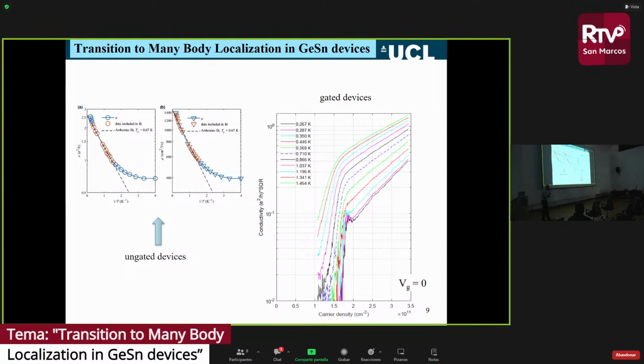So to make the gated devices, we put down a layer of aluminium oxide, a little bit thicker than we heard earlier. It's about 40 to 60 nanometers. And we can apply something like plus minus 20 volts approximately. So this data here is the device conductivity as a function of carrier density. This carrier density is changed with the gate voltage. So this is 0 gate voltage up here. As we apply a positive gate voltage, as I said, this is a hole gas. So if we apply a positive gate voltage, we decrease the hole density, okay?